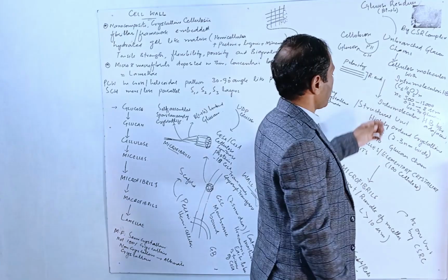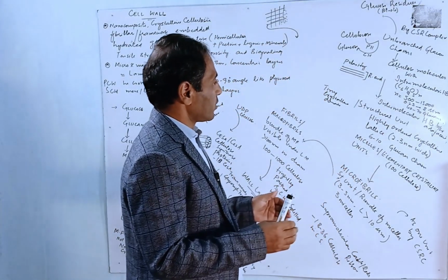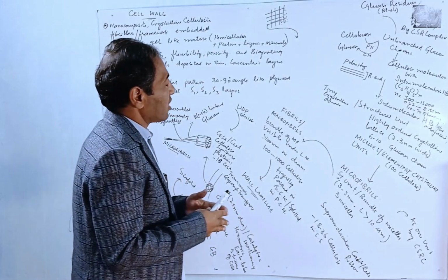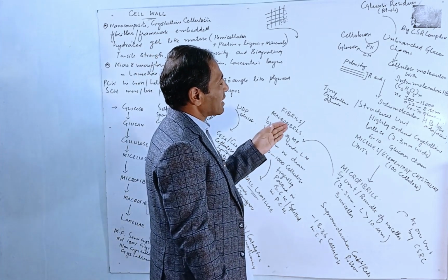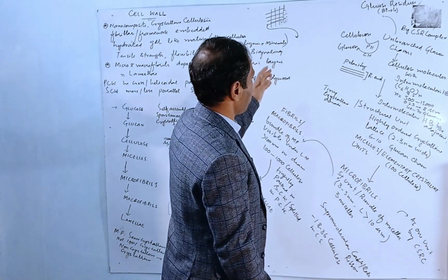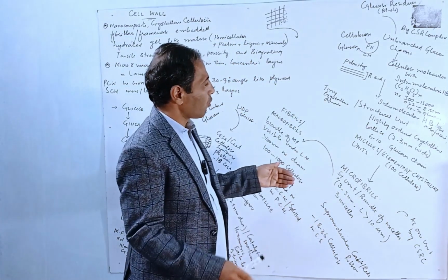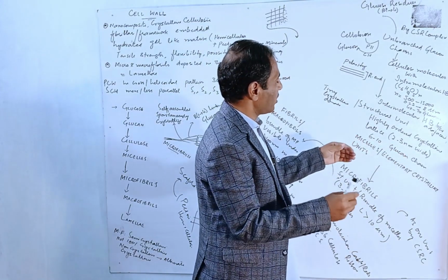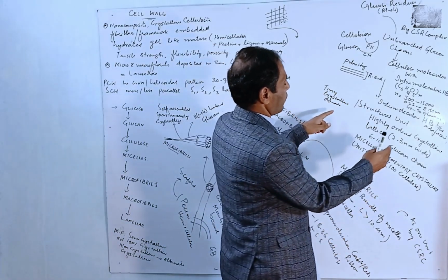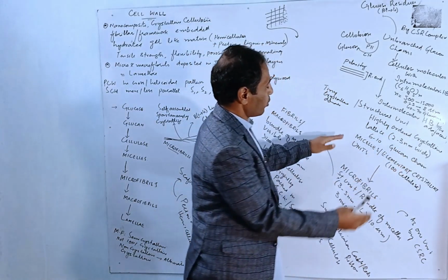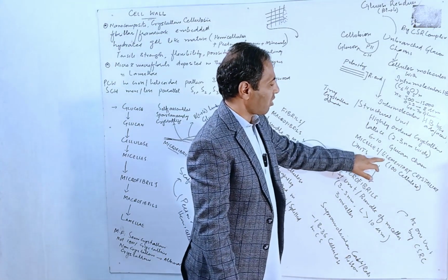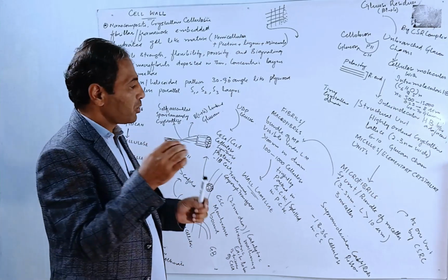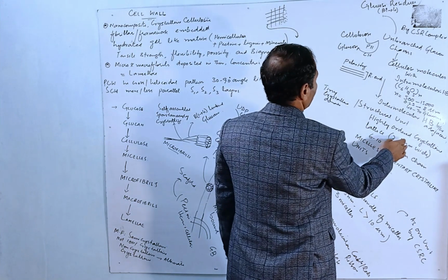Now, the cellulose molecules combine together in different numbers to give us tiny crystalline and non-crystalline domain cellulose fibrils, which are the fundamental structural unit. From 6 to 10 glucan chains combine together, giving us a fundamental unit of the cellulose compound, which is called micelles or elementary crystalline unit. They have a diameter of 2 to 3 nanometers in a wide lattice form.